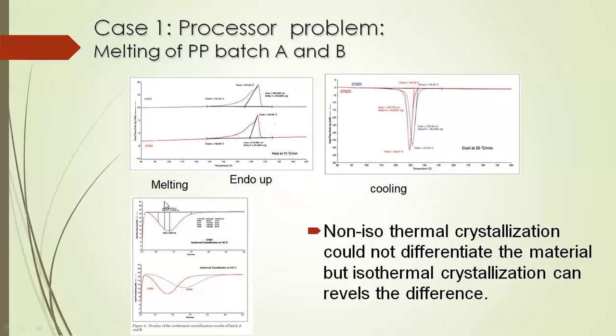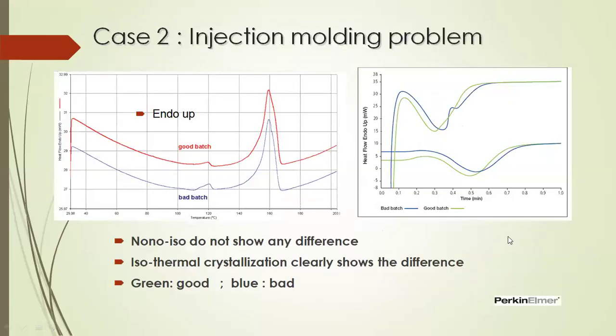But when he did the isothermal crystallization of the good and bad batch at the same temperature, the behavior was different. The batch which passed QC had a different total time of crystallization than the batch which failed. So isothermal crystallization revealed a little bit deeper into the problem, and because of the mold temperature, the manufacturer raised the mold temperature and the batch used to pass. Similarly, in the same injection molding batch, the non-isothermal experiment did not reveal any difference, but the isothermal experiment showed the difference in the crystallization time, and we could shift the process.